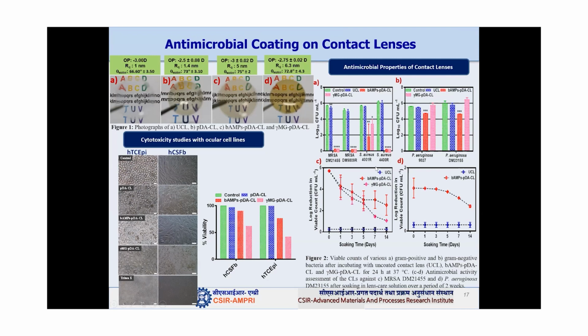Then, because contact lenses are usually kept in lens solution, we checked the efficiency of these lens coatings at different time points, and we found that even after 7 days and 14 days, there is quite a good reduction in the bacterial number, even after soaking. So these coatings are not only antimicrobial, not only safe, but also durable.